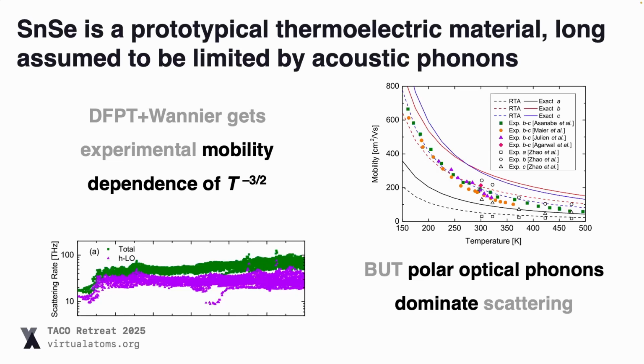The issue is that what kind of started this whole thing is when we looked at one example material, tin selenide. This is a kind of prototypical thermoelectric material, and its mobility has this T to the minus 3/2 temperature dependence, and this is reproduced very, very nicely with the computational methods. So for a long time, everyone had assumed that this was limited by deformation potential scattering. But when you actually look into the calculations, it turns out that polar optical phonons are what are dominating, not deformation potential scattering. So this is one of the most well-studied materials. We thought, what's going on? Could there be more out there?